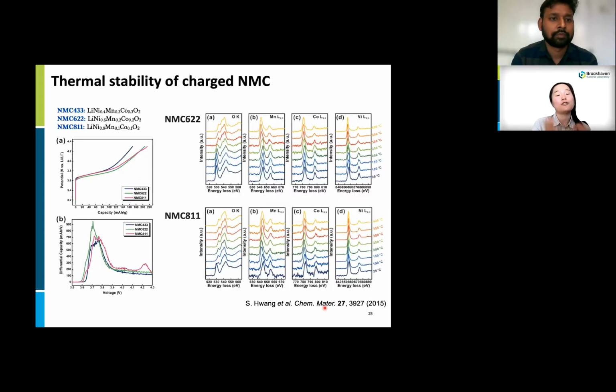To find the good composition of NMC materials, I tried 3 different compositions of NMC compounds. In the case of the 433 composition, it delivers much lower capacity than the others. So I'll exclude this composition for our discussion. NMC622 delivers comparable capacity to NMC811, which is quite good.